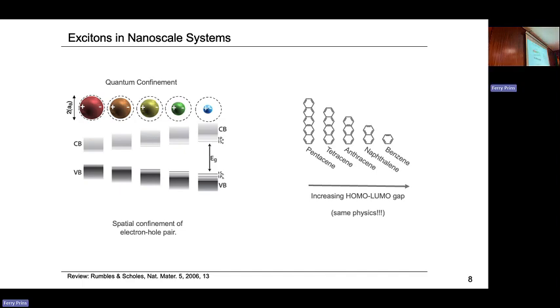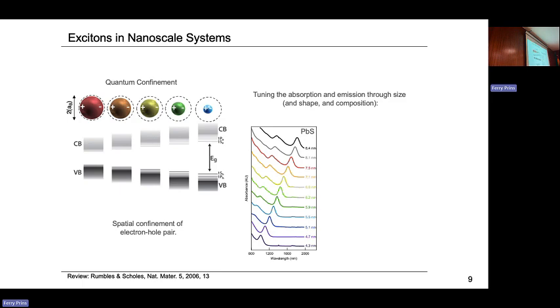Okay, so here's an example of this effect, one of the textbook examples. This is lead sulfide. We go from a relatively large particle of 8 nanometers with an emission wavelength in the near infrared, 1800 nanometers. As we go from 8 to 7 to 6 to 5 to 4 nanometers, we shift our emission wavelength from 1800 nanometers down to 900 nanometers.